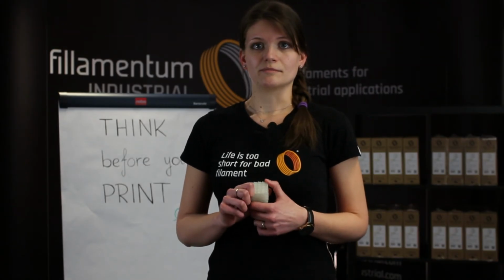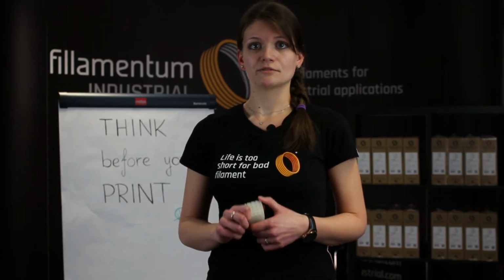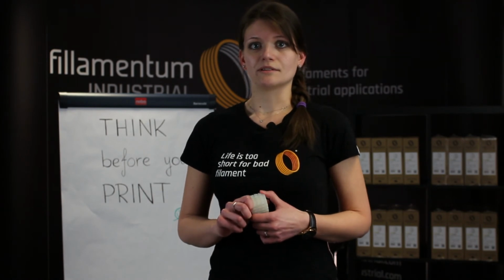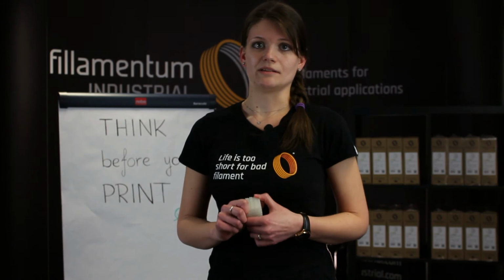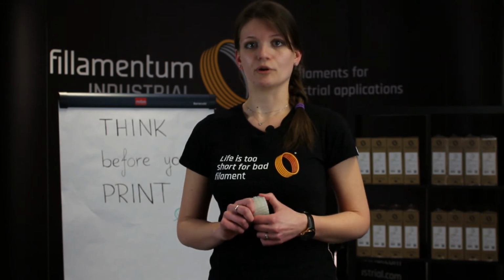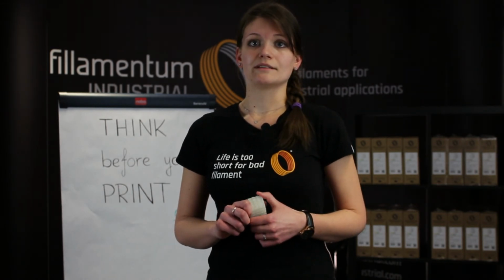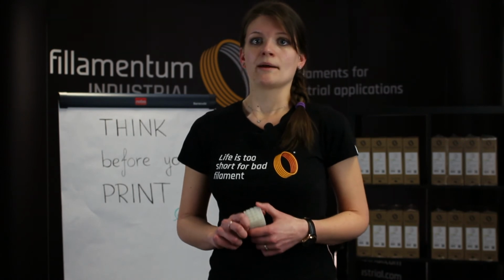It was measured that 100% of CO2 was released by bacteria within 90 days in industrial compost and also within 120 days in home compost. It means that this material can be biodegraded also in home compost in 100%.